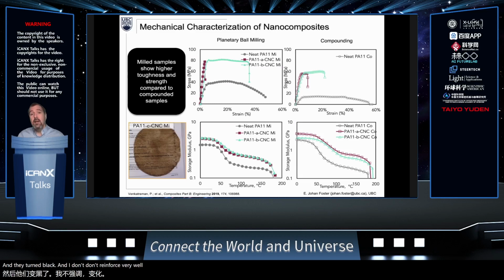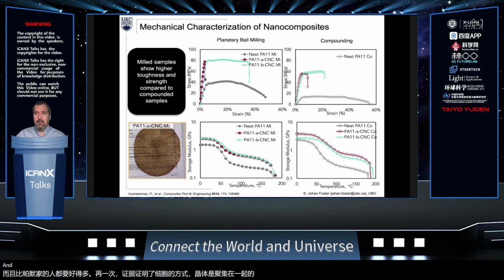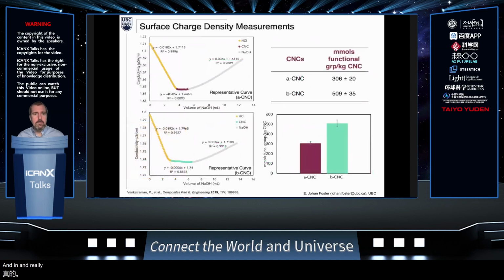Okay, but this shows the effect of both ball milling and then compounding of this material to get a reinforced composite. So this is polyamide 11, and drastically better properties than the neat polymer. So again, evidence that those cellulose nanocrystals are held together and really reinforced. Okay, and we attribute that dispersibility somewhat to the charges on the surface. And if you do this in the wrong way, if you get very, very highly charged surfaces, they become less thermally stable.